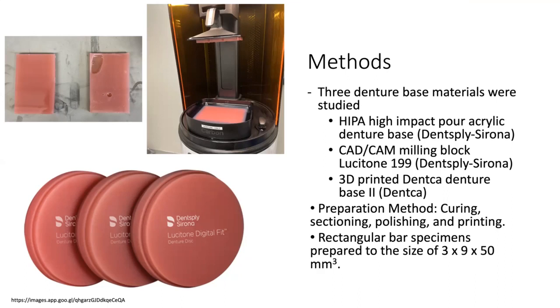Lucitone block specimens were sectioned using a Buehler Isomet 5000 diamond saw. The HIPA specimens were fabricated by curing the powder liquid mixture in a silicone rubber mold at 45 degrees Celsius for 30 minutes at 1.5 bar and then sectioned. And then the 3D printed specimens were fabricated using a Carbon M series printer. After the specimens were fabricated, they were all polished sequentially to 15 micron grit using the Buehler EcoMet, and they were stored in water at 37 degrees Celsius for 10 days before testing.